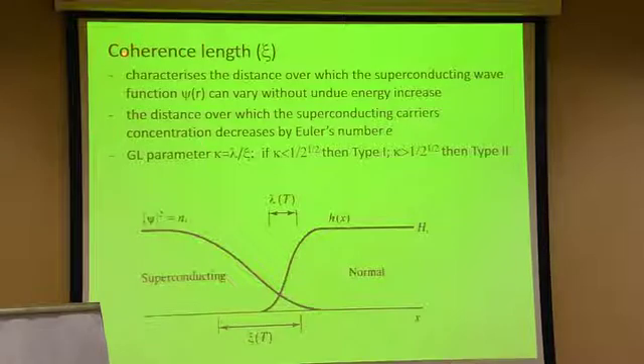And if we compare these two characteristic lengths, this Ginzburg-Landau parameter is k equals lambda over xi. It has been shown through analysis of the free energies at the interface between superconducting and normal that if k is smaller than 1 over square root of 2, we have type 1, or if k is larger than 1 over square root of 2, then we have the type 2 superconductor.